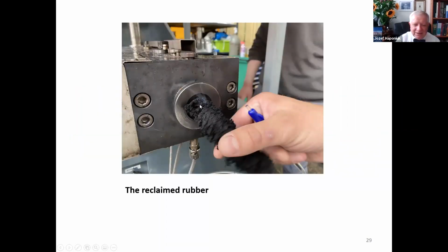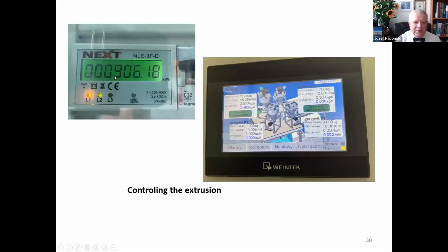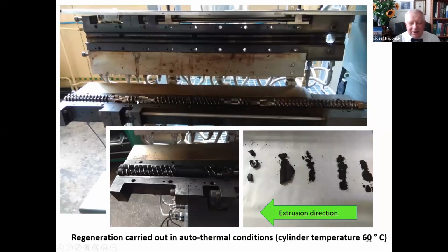That it is at higher screw speed, and the temperature is already higher, and we can see some fumes which we do not like. We are aiming at low content of organic volatile compounds. We can also measure the energy used for this process and observe all parameters. And here, this extruder is very convenient for research because we can open and see inside